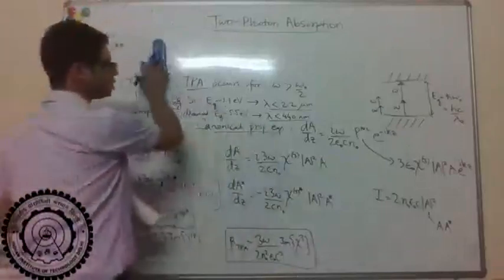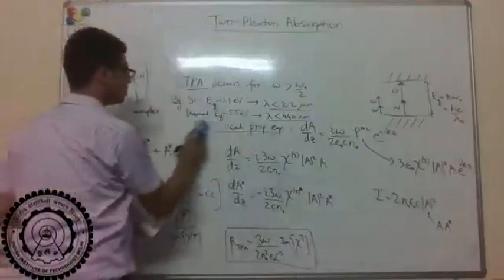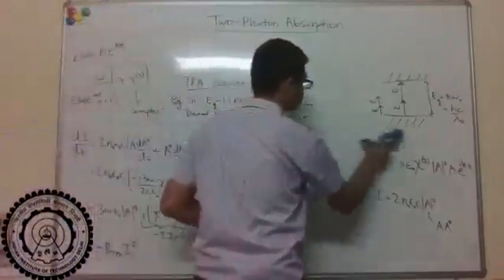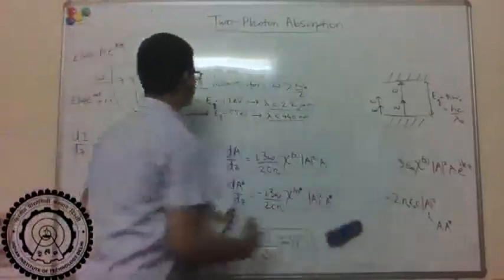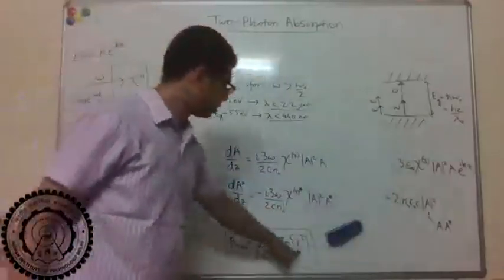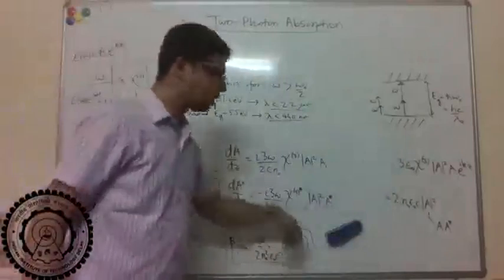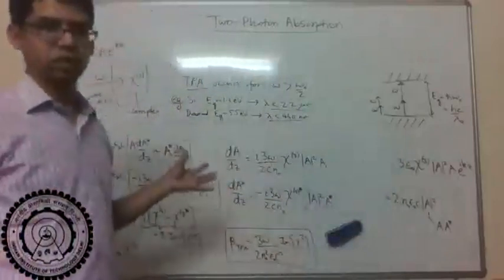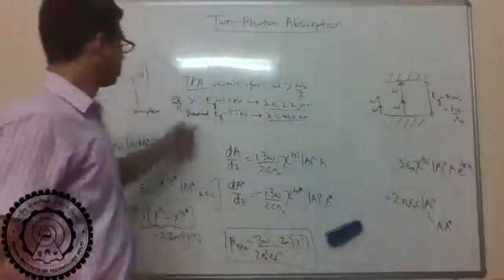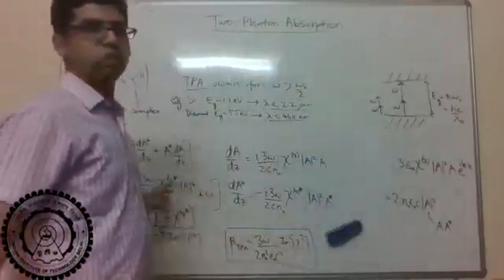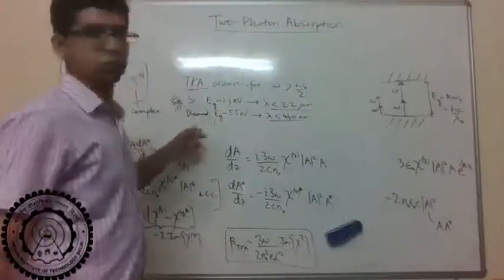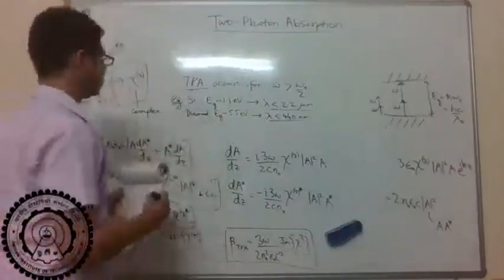Silica, sort of the most widely used optical material, has an even larger band gap. So of course there's a trade-off, right? As I'm going to larger and larger band gap, we saw that the chi3, for example the real part of chi3, which I'm interested in for nonlinear interaction, also goes down. So bigger band gap gives you bigger range of operation, but it also gives you smaller interaction.